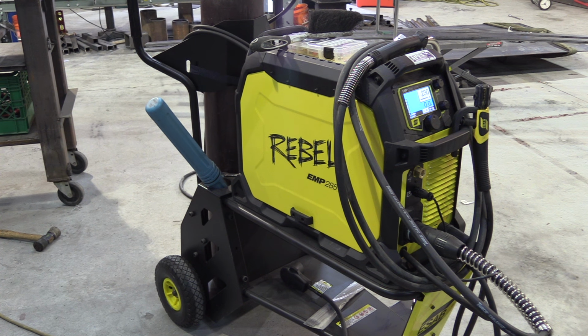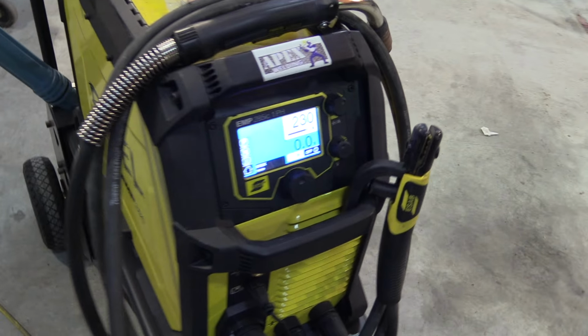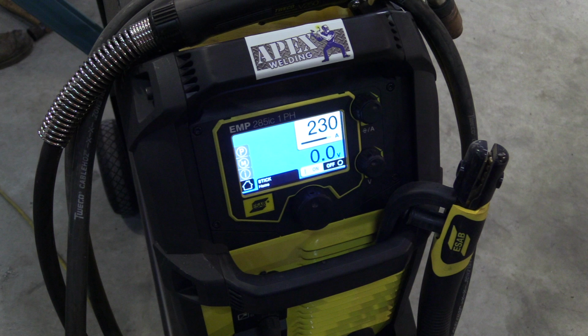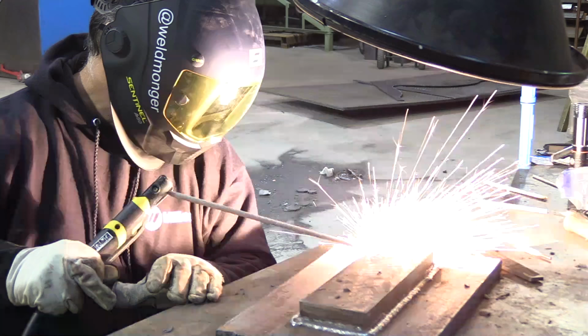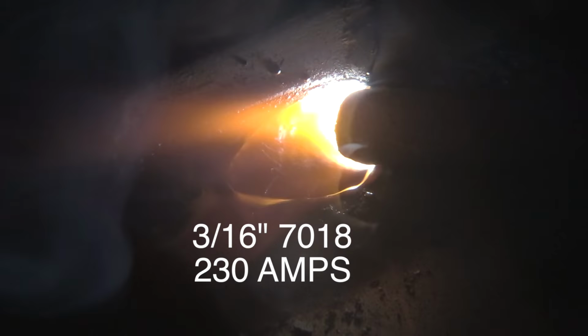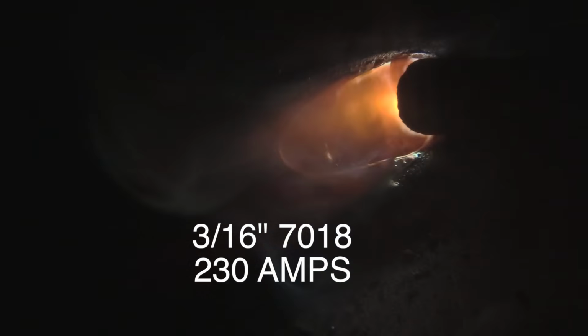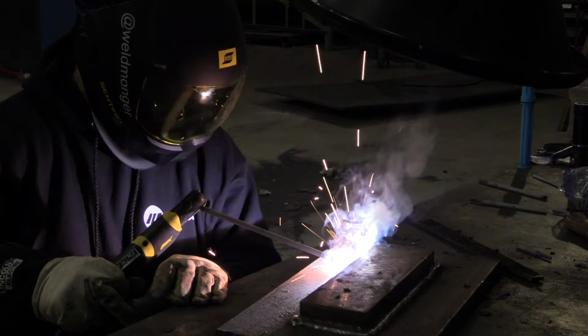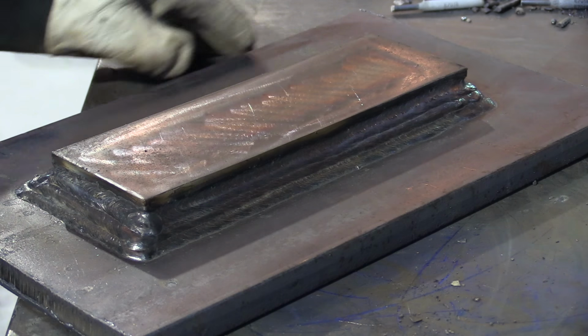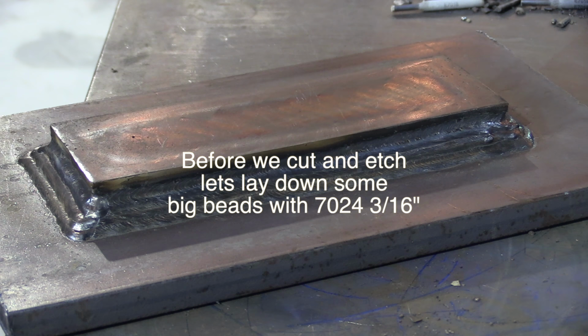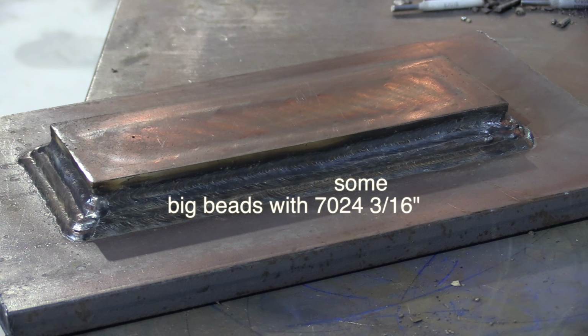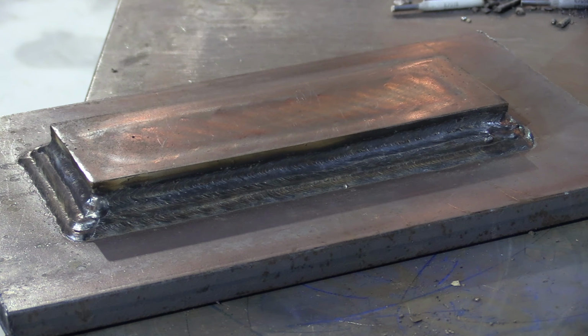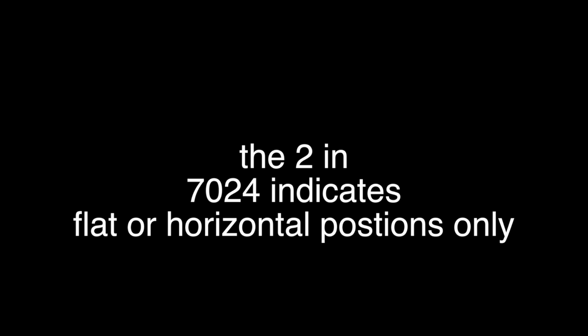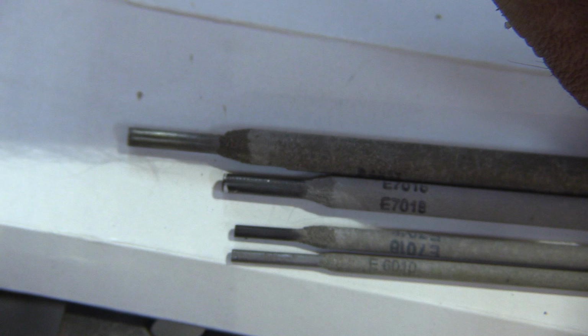Let's take a really quick look now at the previous stick welding video I did where I was using 3/16 diameter 7018s at 230 amps. The 7018 puddle is much easier to distinguish between molten metal and molten flux than with a 7024. That is one big difference. That, along with the fact that a 7024 is not rated for all positions. So even though they say it's for flat and horizontal, when you start getting into more horizontal rather than flat, you can get some issues. And we're going to see some of that today.